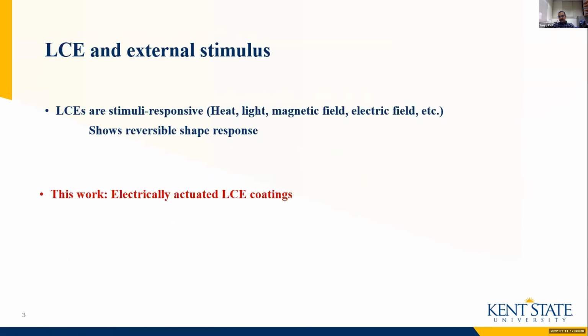So in this presentation, I'll be focusing on electrically actuated liquid crystal elastomer coating. For that liquid crystal elastomer, we have monoacrylates and diacrylates. Upon polymerization of monoacrylate liquid crystal monomers, they make a chain, and diacrylate liquid crystal monomers cross-link. So finally, it makes a network.